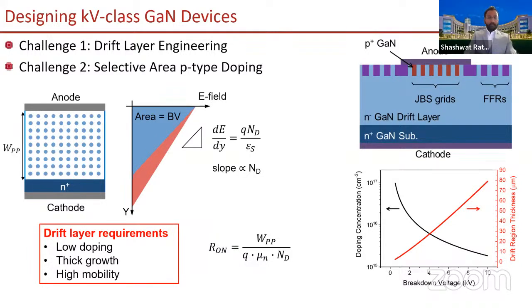It's very sensitive as such to the synthesis technique that we use. If you look at the trade-off between on resistance and doping, when you reduce the doping and increase the thickness to increase your breakdown voltage, it always also increases on resistance. So there's always this trade-off that you work with.